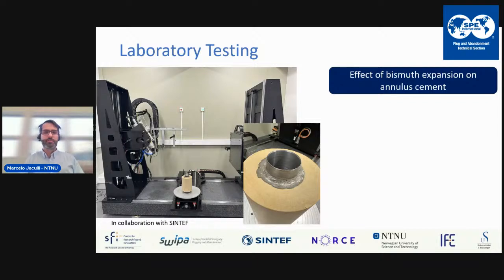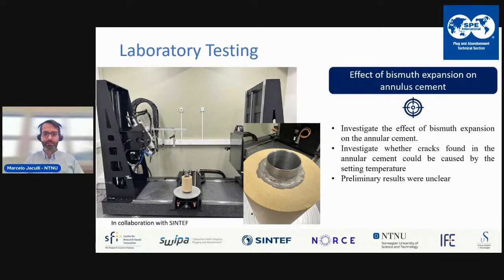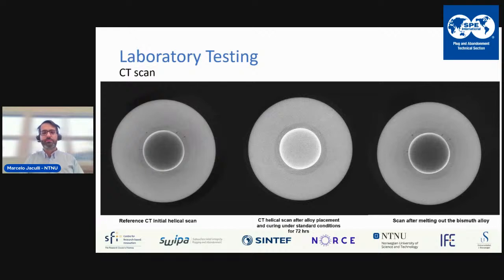This can cause some deformation on the cement as well. But depending if the cement has cracks before, you could close these cracks because of this deformation, or if it's not cracked, you might cause the cracks yourself. We were not sure what would happen in that case, and unfortunately we were not really able to give clear results because from the images, it was not very clear what kind of contribution the bismuth plug had.